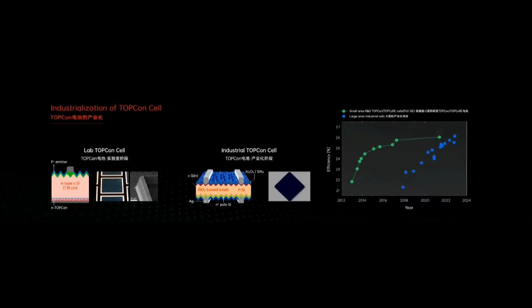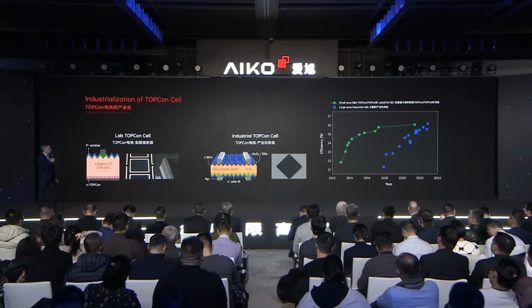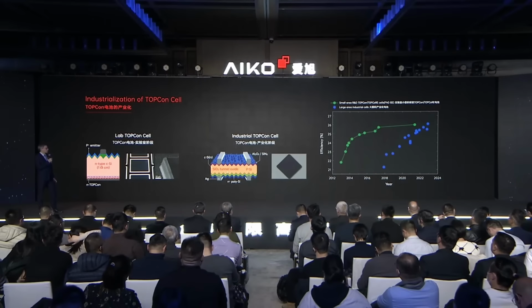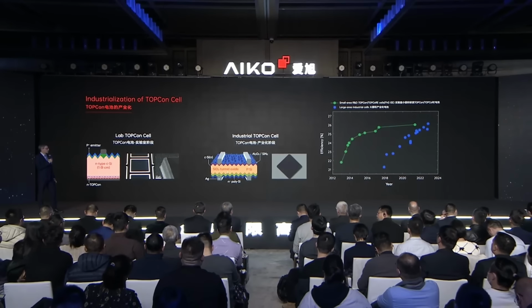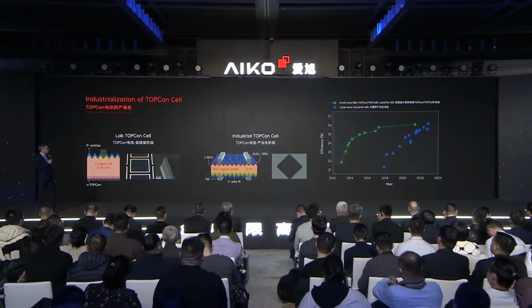And now, a few years later, there was quite some R&D activity in the industry, especially here in China, to industrialize the TOPCon cell, where the industrial version is by nature bifacial. We have screen printed contacts on both sides, and you can see here with the blue dots the impressive learning curve, where we now are also for champion cells at 26% efficiency.